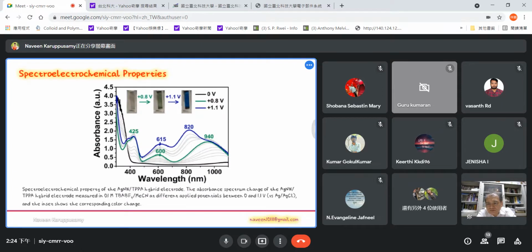The next one is spectroelectrochemical properties. After the passivation layer over the silver nanowire, first they performed up to 0.8 volt. There is a change in the passivation layer from white color to green color. After the potential changes to plus 1.1, the green color changes to blue color. We observed this spectroelectrochemical property with the absorption spectrum.